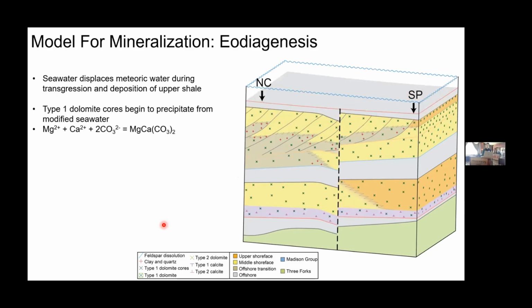So this meteoric influx was then followed by a large transgression during the deposition of the upper shale. So you probably have a transgressive ravinement surface at the top of the middle member. That would have resulted in a change in the pore fluid, something more akin to marine seawater as a result of that transgression. And from that, we think that was the source for the initial type 1 dolomite cores to form.